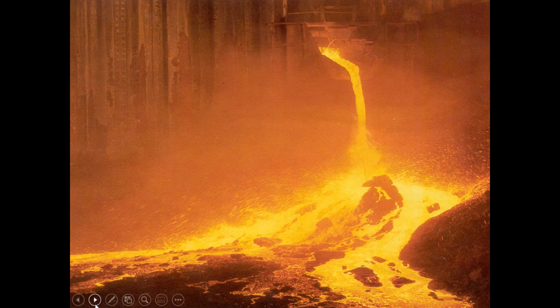Now, it's fairly common to see concrete paving around most of the steel facilities in North America made with blast furnace aggregate. It's a perfectly fine aggregate. It's air cooled. It is slightly more porous, so our concrete guys have to know how to handle it to make sure the aggregate is soaked and so forth, and it makes perfectly fine concrete.